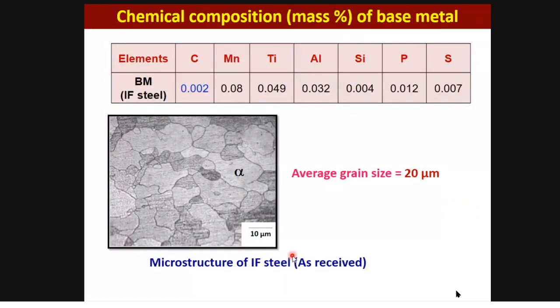So this is the chemical composition. You see that carbon content is almost 0.002, that's the carbon content. And this is the microstructure of the IF steel, and it's full of ferrite grains, alpha grains. Its average grain diameter is 20 microns in the as received condition.